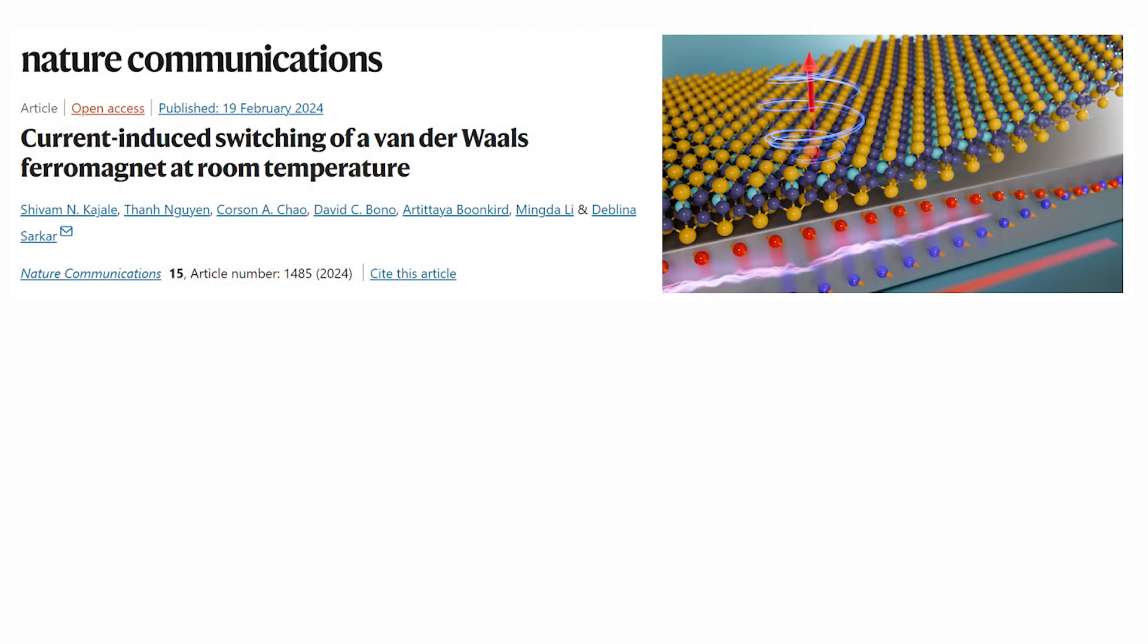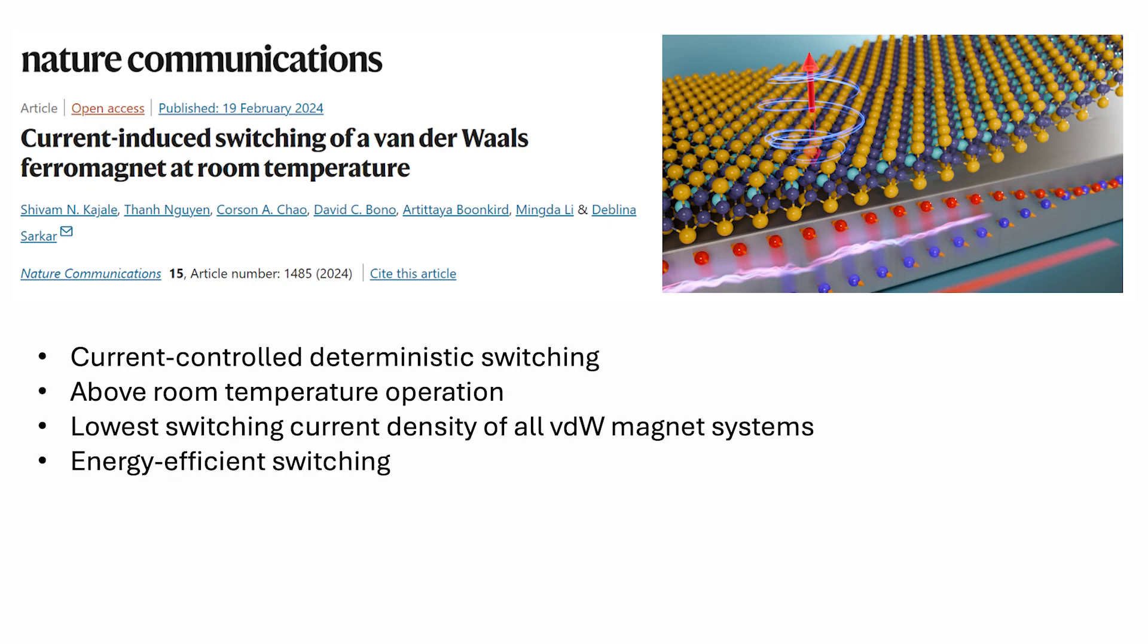By combining a new material with superior properties and the spin-orbit torque switching mechanism, we have created a solution for switching Van der Waals magnets electrically above room temperature. Notably, our device also requires the lowest switching current density among all Van der Waals magnet-based devices, proving its effectiveness for achieving energy-efficient computing. With this critical milestone achieved, the path to integrating 2D magnetic materials into scalable, energy-efficient spintronic devices has opened up.